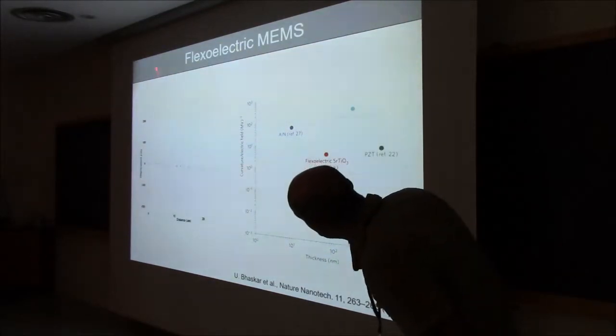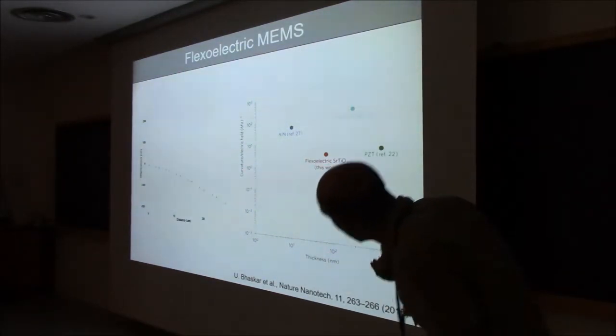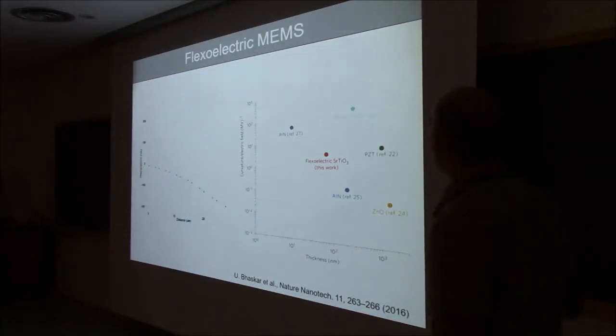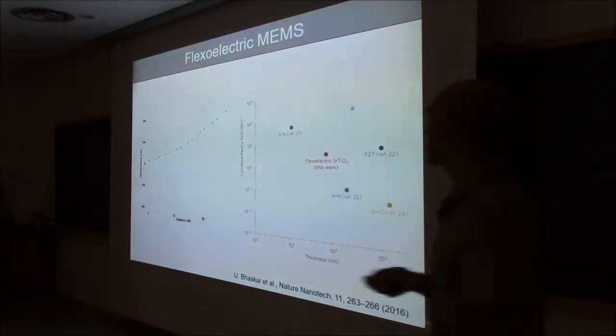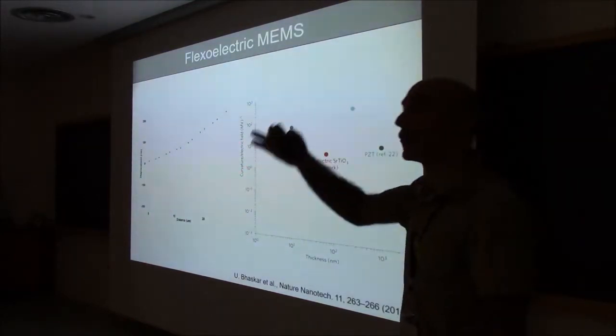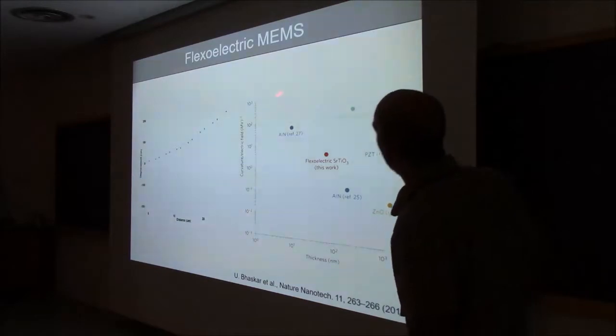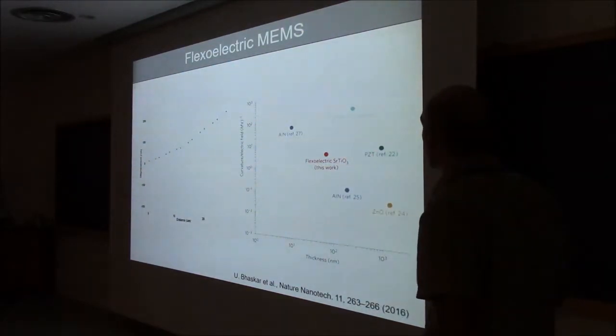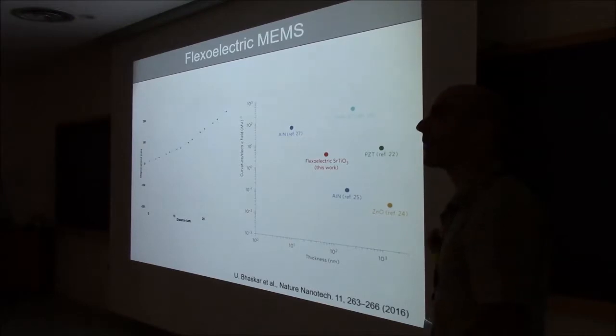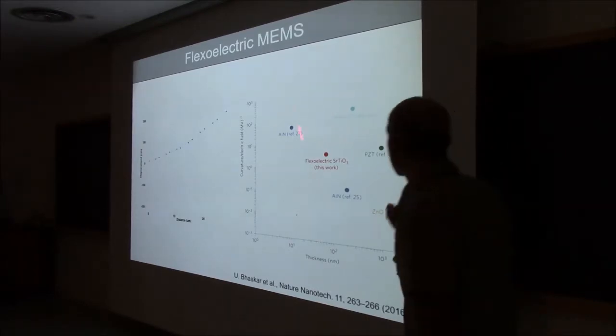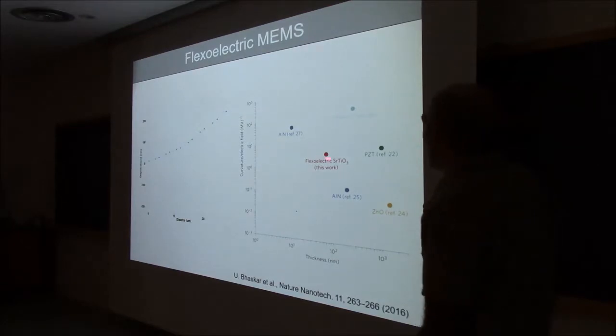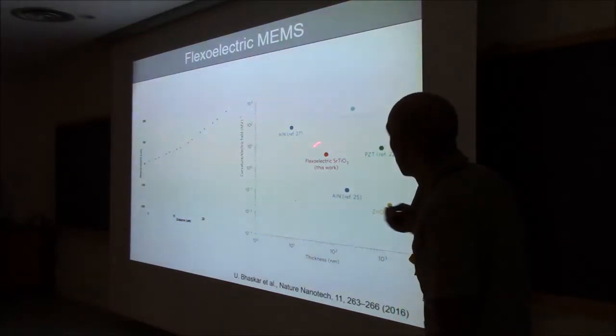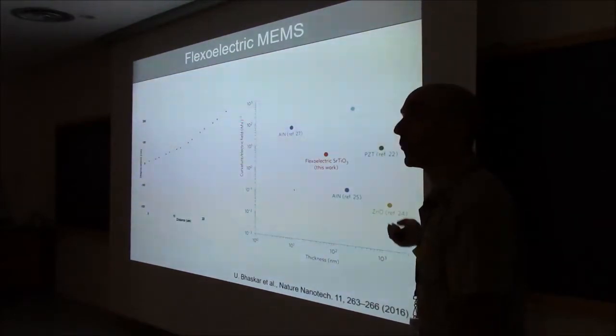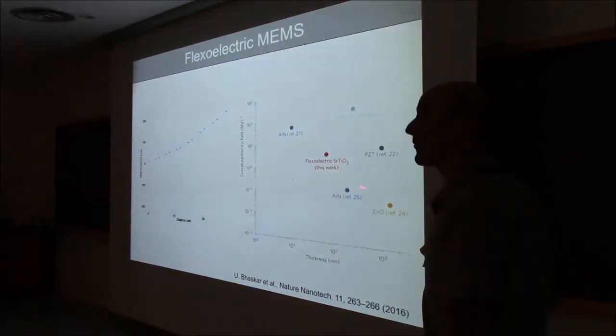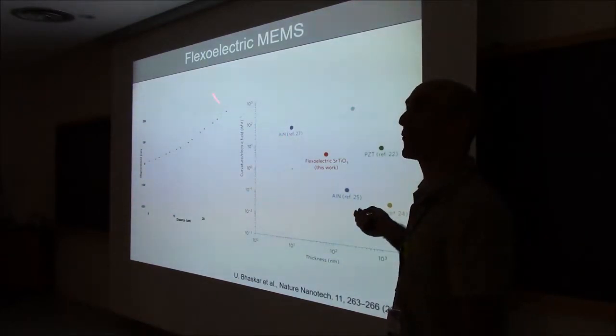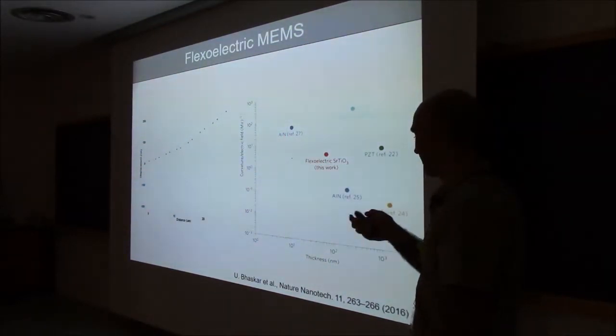This is the displacement on one of our STO membranes, and you can see it's pretty huge. And when you compare the flexoelectric performance of this STO flexoelectric actuator with the performance of piezoelectric bimorph actuators, you can say it's in the mix. It's competitive. It's not the record. It's not as high as these things would be, but it's big. And in theory, if you could make this a bit thinner, it should jump up because this goes as 1 over the cube of the thickness. We haven't managed to make it thinner, so we haven't beaten the record. But if somebody wants to try, it's a good challenge.